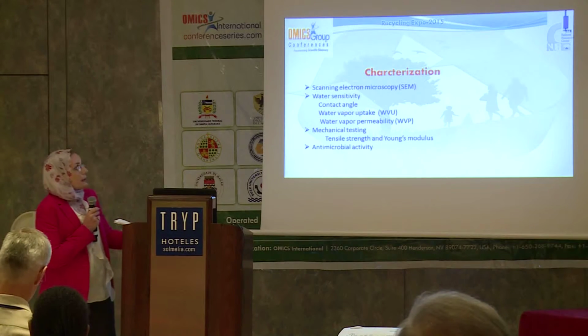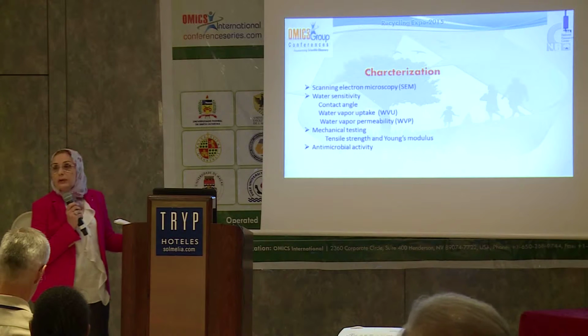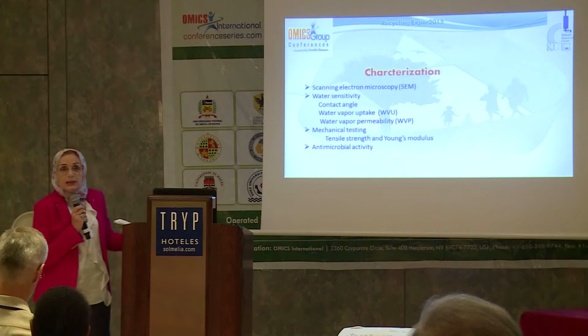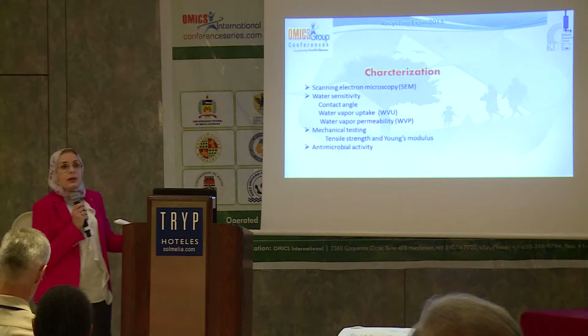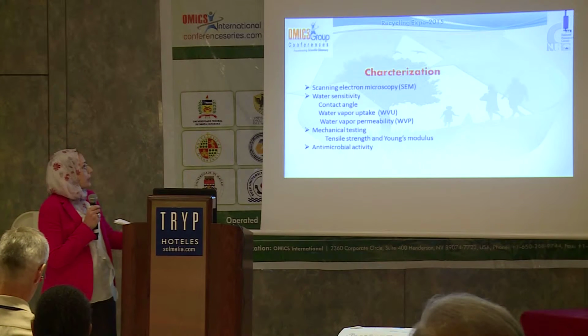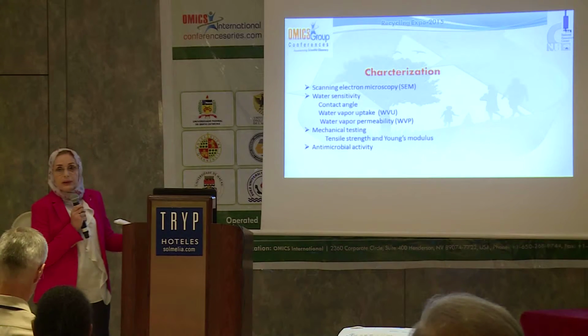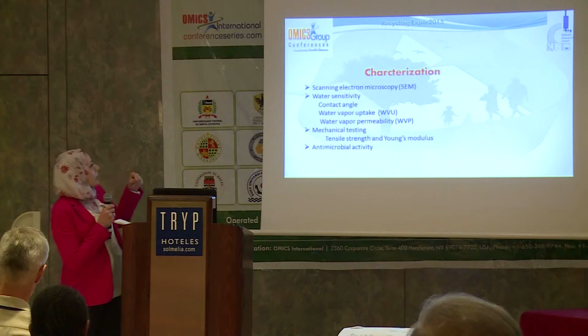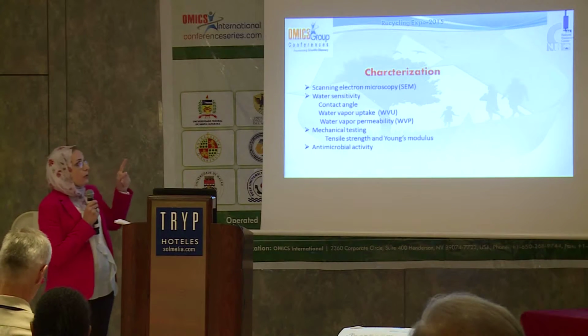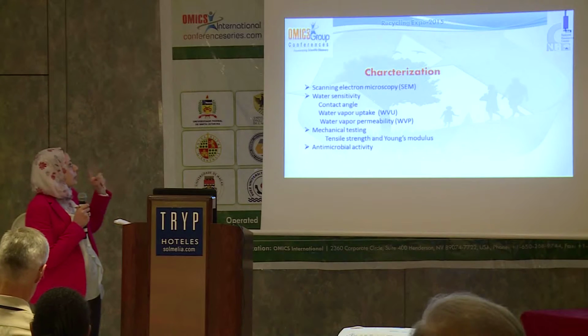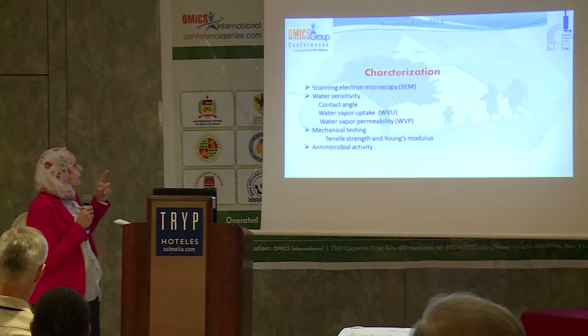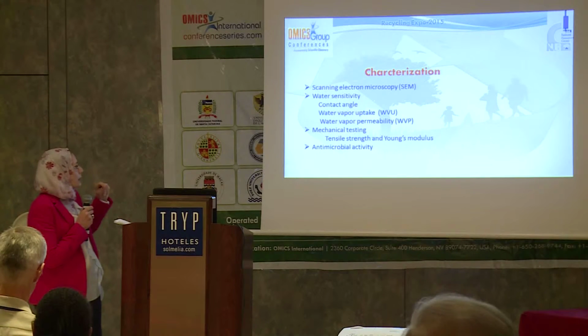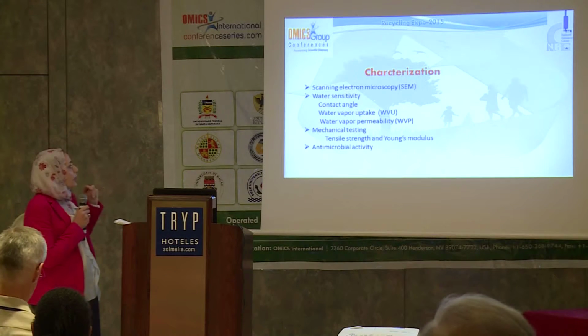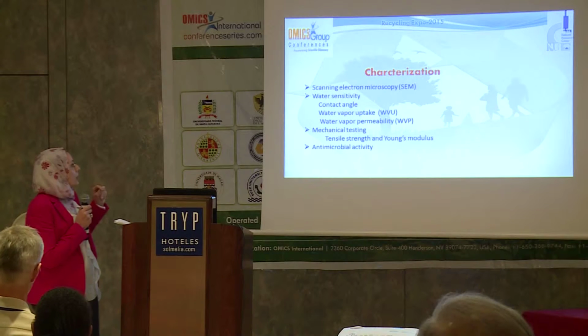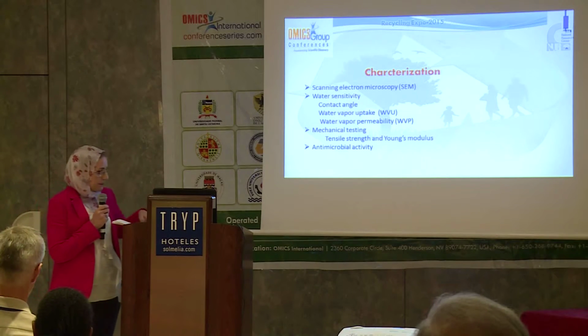We prepared wheat gluten films filled with cellulose nanocrystals at different percentages and titanium dioxide. We characterized the prepared films by scanning electron microscopy, and the water sensitivity was characterized by contact angle, water vapor uptake, and water vapor permeability. The mechanical testing was characterized by tensile strength and Young's modulus, and also the antimicrobial activity of the films was determined.